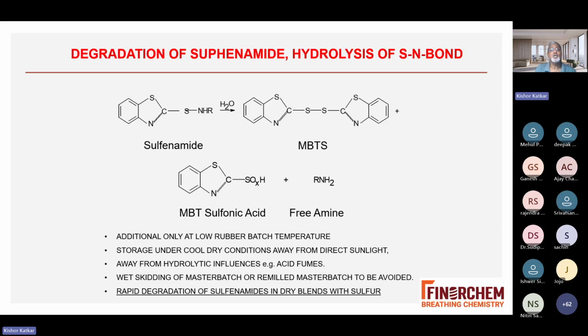The quality should be good. What do I mean by quality? When degradation happens, it forms MBTS, and MBTS is reflected in MI, methanol insolubles. You have to check the insolubility. The higher the MI, obviously MBTS will go up, so your scorch safety will get affected. Your T90 will not be affected, but scorch safety will. So you should have a reasonably fresh and stable product. Also there is free amine. When your product decomposes, it forms MBTS and amine, and this free amine will act with MBTS and your scorch safety will further come down. Obviously, your T90 will come down.